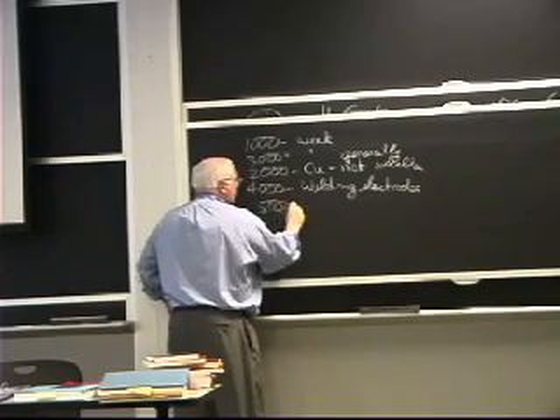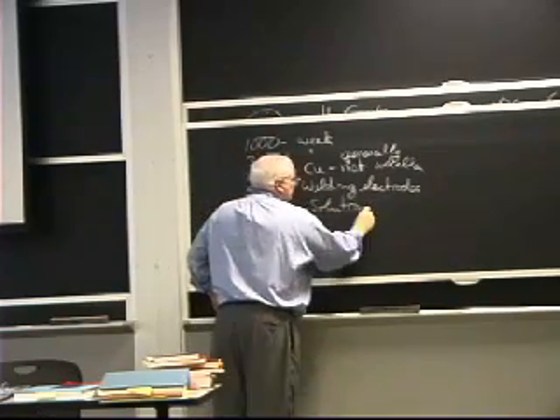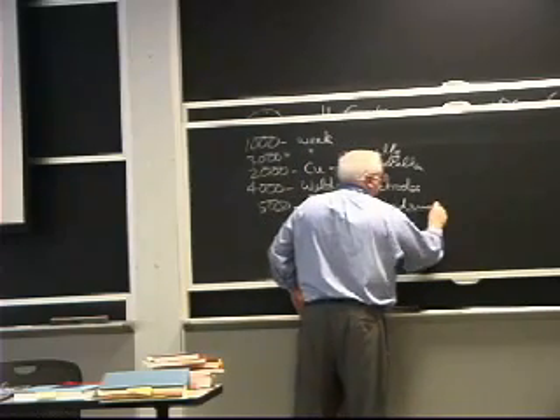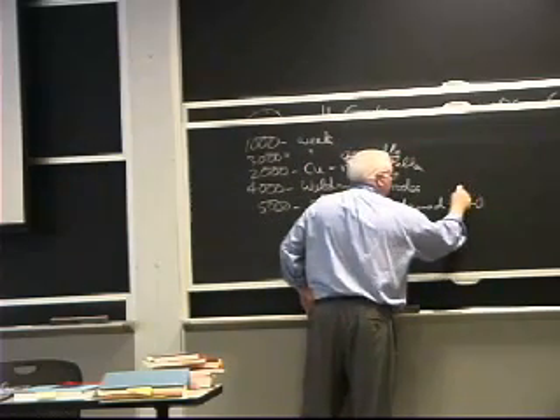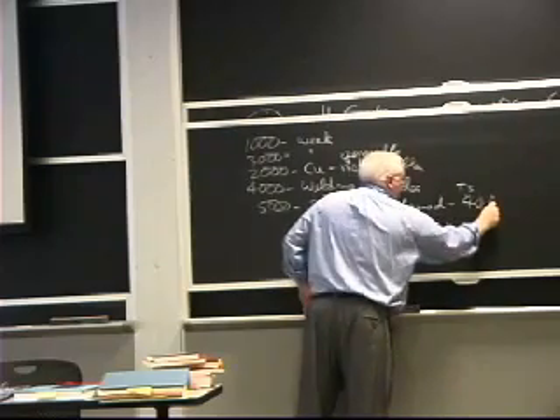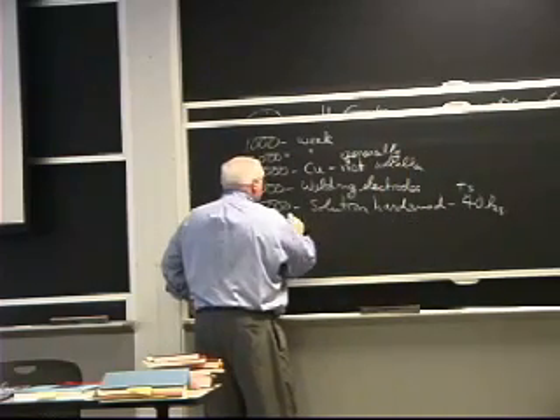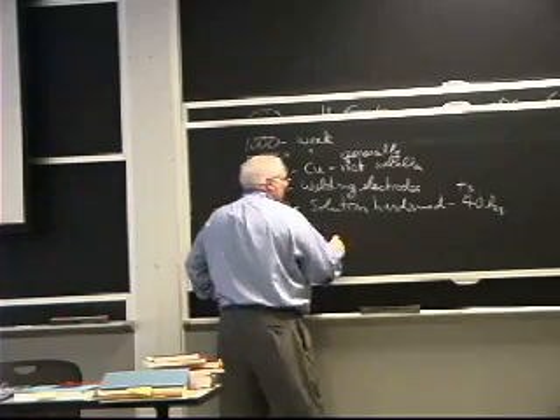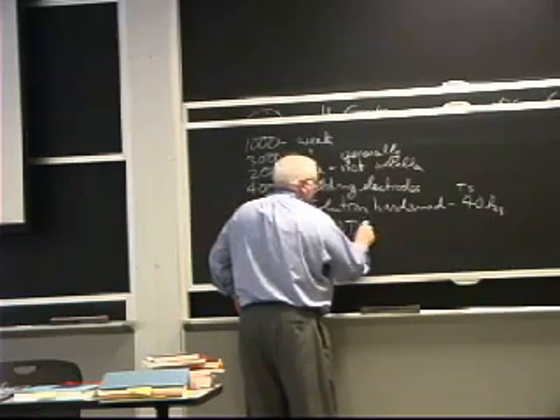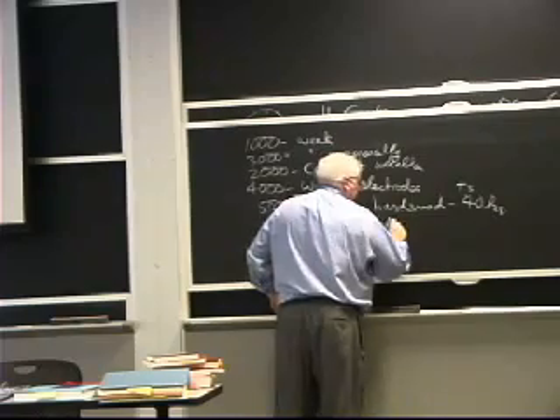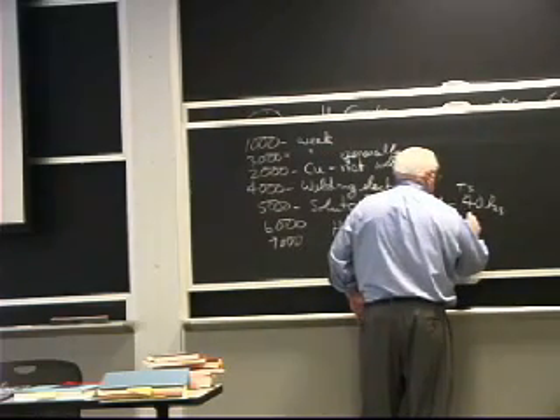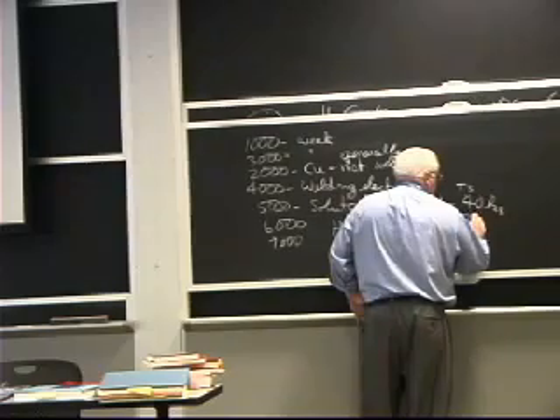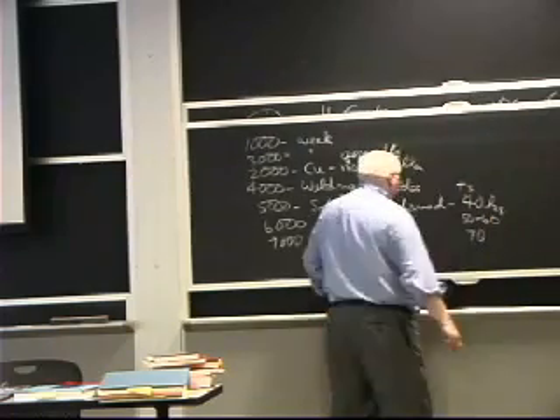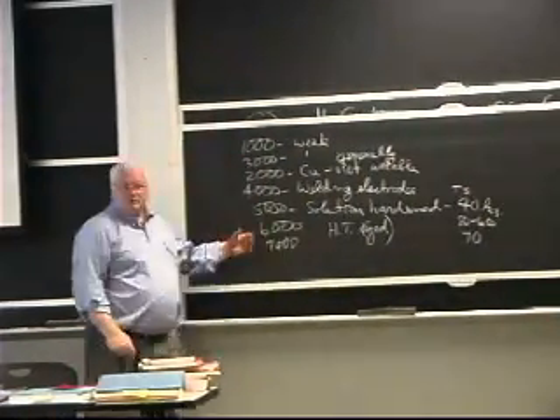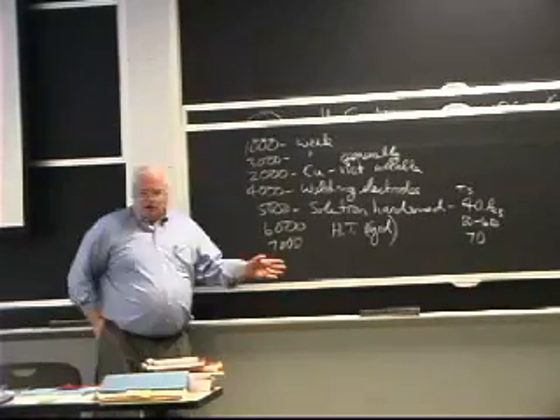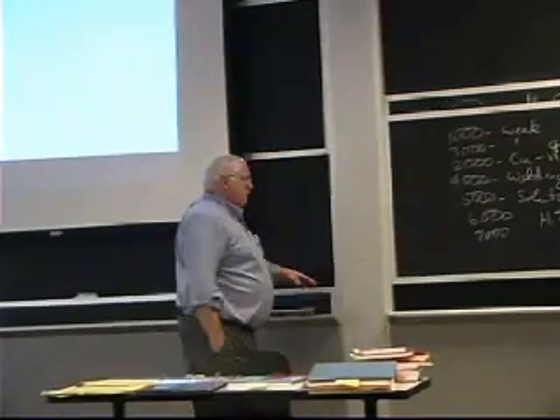5000 is solution hardened, and they'll have a tensile strength of about 40 KSI. The 6000 and 7000 are heat-treated, aged, precipitation heat-treated. The 6000 series might be 50 to 60 KSI tensile strength, and the 7000 series will be up to 70 KSI. There's an 8000, there's a 9000 series, but they're kind of specialized. We don't run across them much. Well, not for welding anyway.